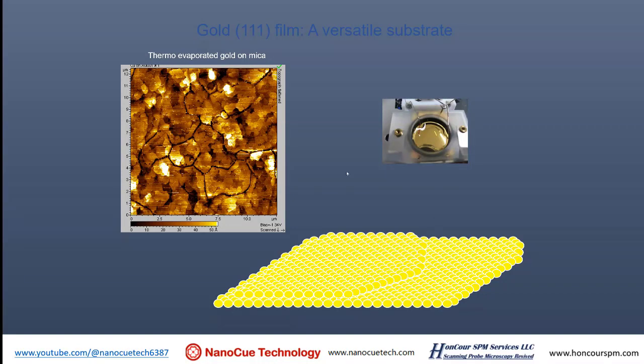Okay, here in the lower right corner, I put a drawing of an imaginary view of the gold 111 surface. Basically, it's a bunch of balls, gold atoms. You can think of them as balls. And then you pack them together, and they form a hexagonal structure. And then a second layer can pack on top of the first layer. Between the first layer and second layer, you can see there is a step. That's the atomic step. And this atomic step is only 2.35 angstrom thick, or 0.235 nanometers. Okay, so that's the step. If your sample is clean and flat, steps are everywhere.